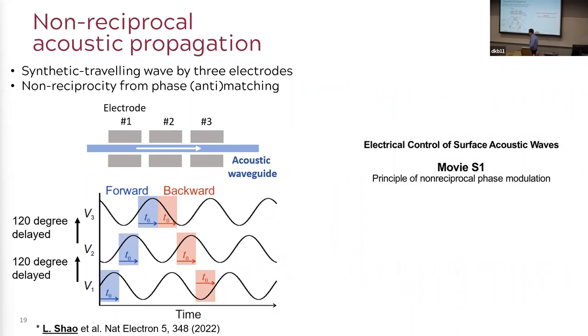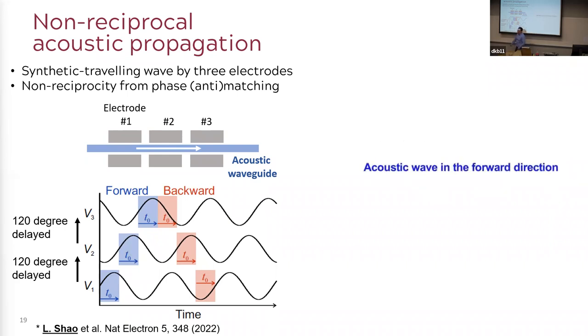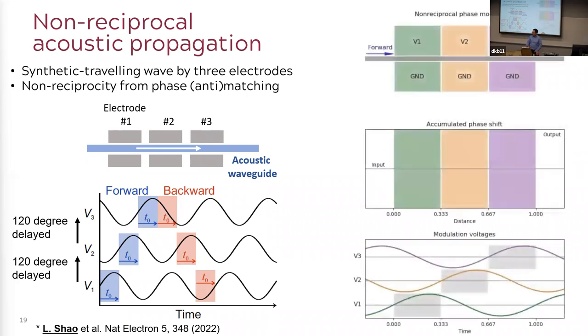One very interesting thing is that we can have a non-reciprocal effect. The way we generate non-reciprocal transmission is that we use it in propagation. We separate it into three electrodes and apply signals with different phases on these three electrodes. By doing so, the acoustic wave coming in the forward direction sees the same phase, so everything accumulates. But a wave coming in from the back will cancel out.